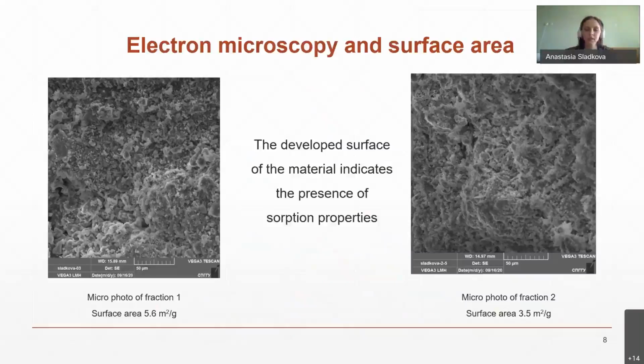Some scientific works highlight the possibility of using various slags as sorbents. And in order to evaluate the possibility of sorption on the slag, it was necessary to look at the particle surface and measure the surface area. On the slide, you can see the images of the surface of the two fractions. And the particles have a developed surface, which allows us to assume the presence of sorption properties of the material. Also, we measured the surface area of the fractions, and the smaller fraction, number 1, has about 5.6 square meters per gram surface area, and the larger fraction, fraction 2, has about 3.5 square meters per gram.